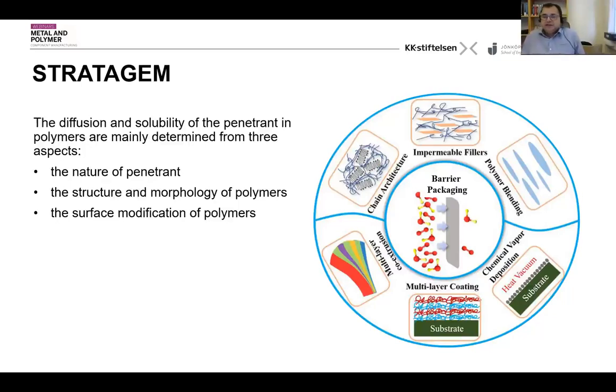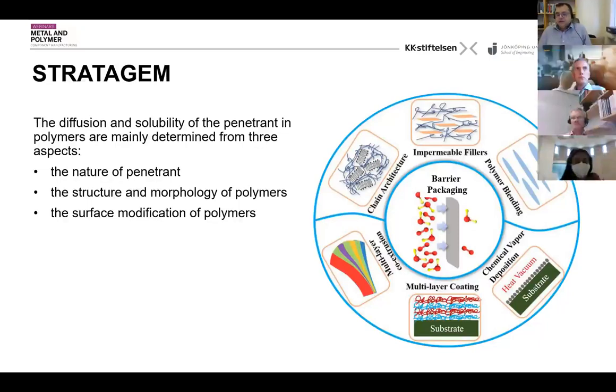Last, since diffusion is actually a surface phenomenon, we can create some layers of material on the outside surface of the polymer, which can act as a barrier in the first place. So the way of improving the barrier properties is that the polymer substrates are coated with barrier layers. We can use different kinds of coating techniques such as plasma or corona treatment. And for instance, chemical vapor deposition is one technique which could also be used to deposit high barrier polymer films on the substrates. Next slide.